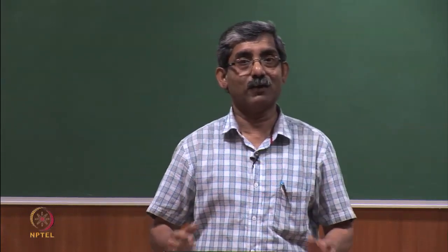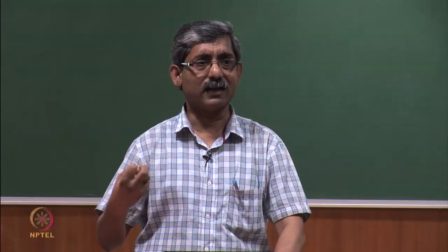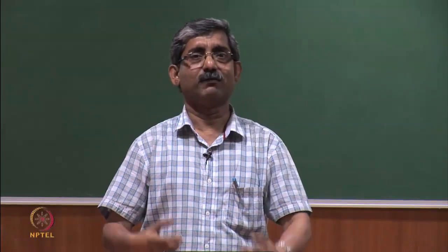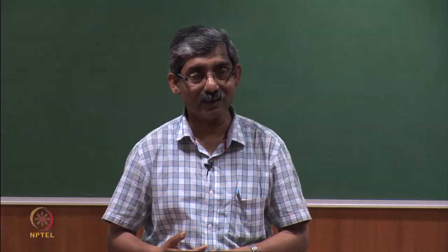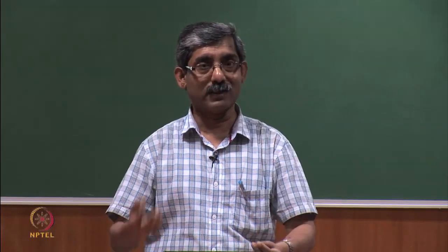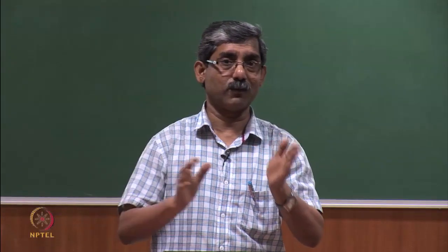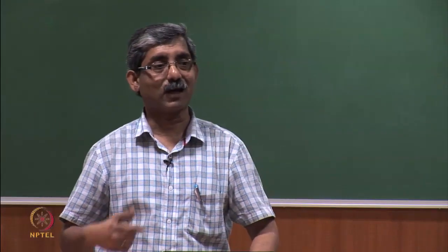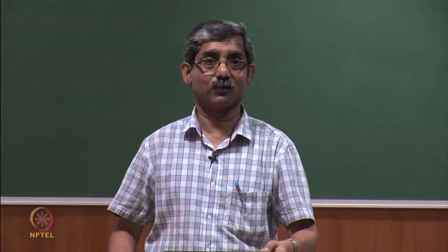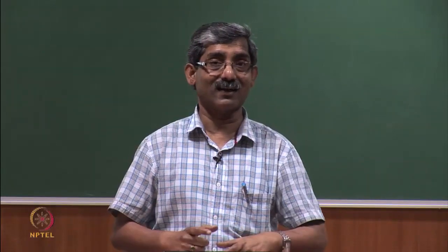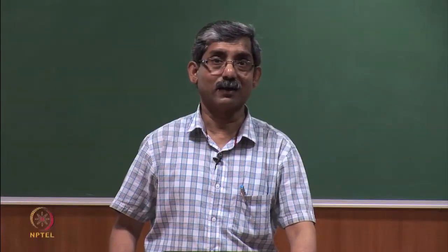The through air bonded non-woven fabric has its characteristics: it is highly bulky and a high amount of air is entrapped inside the structure, and the fabric is bonded. So, its resilience is very high, it recovers from compression and retains its structure and pore structure. So, it was thought that this fabric will give better thermal insulation, and we also wanted to study the evaporative resistance, to use this fabric as one of the layers in extreme cold climate clothing, mainly the middle layer.